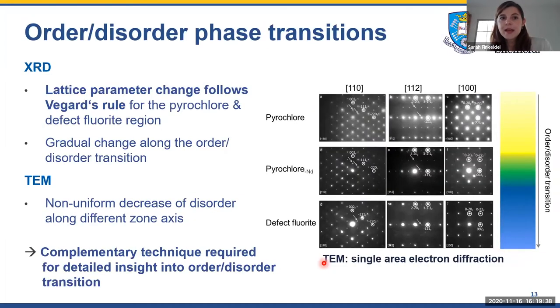So this is a project that was done in collaboration with the University of Sheffield, with Dr. Martin Stennett and Professor Neil Hyatt. And what we did is we performed X-ray studies, and we could see that in the pyrochlore region and in the defect fluorite region, our lattice parameters followed Vegard's rule. And we observed a gradual change along the order-disorder transition.